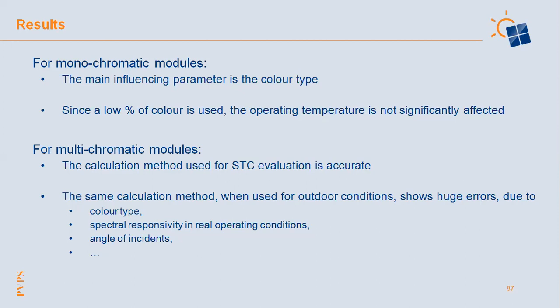But for the monochromatic modules, in this experimental campaign, we can say that the main influencing parameter is the color type. And moreover, even if you can see the color on the modules with this low percentage of color used, the operating temperature is not significantly affected. So the electrothermal behavior of such modules is good.